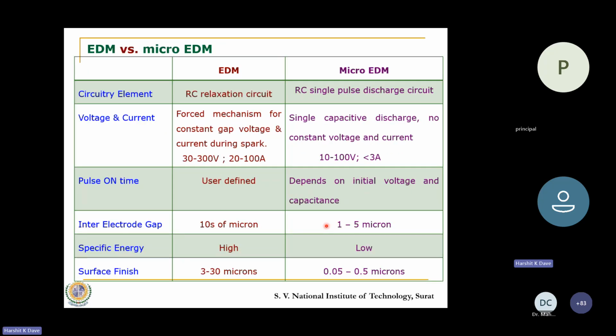So now when I go to the micro domain, what is the difference that I observe between a regular EDM process and a micro EDM setup? In regular EDM, we use an RC relaxation circuit, but here we use an RC single pulse discharge circuit. At a time, my focus is to generate only a single pulse. I don't want to generate thousands of pulses in a second. Once I generate a single pulse, of course, it is generated in 10 microseconds, and one cycle is over. So I keep on conducting thousands of cycles.